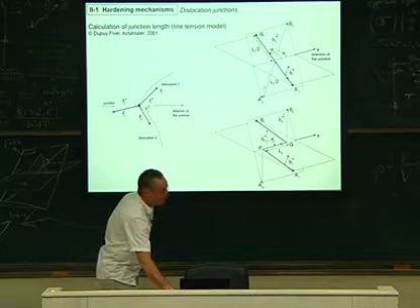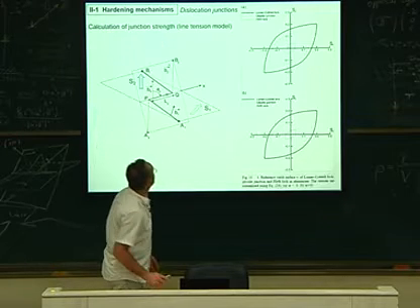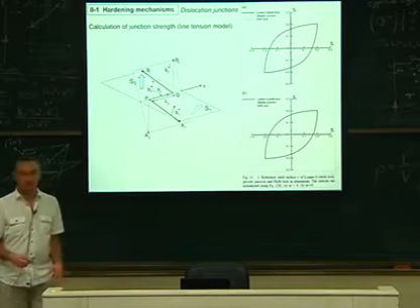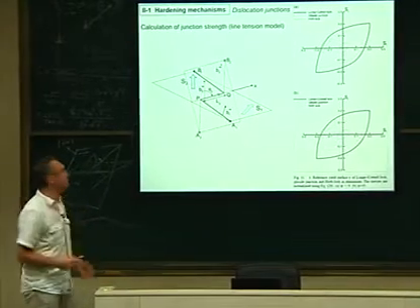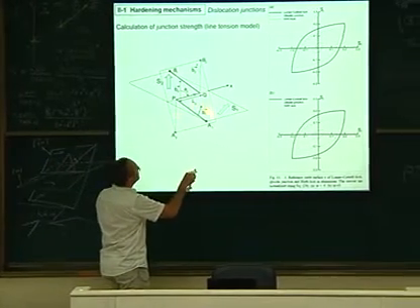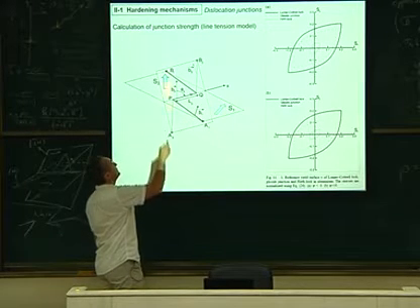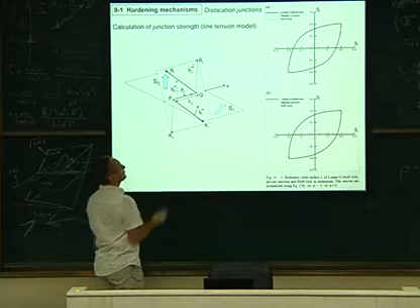So this is for the length. And now, as soon as you have created your dislocation junction like this, you can break the junction, because the idea is to measure the strength of the junction. So what you do is you take your junction and you apply a shear stress S1 in the first slip system and a shear stress S2 in the second slip system, along the Burgers vectors.